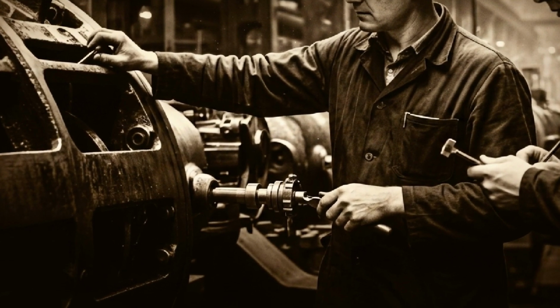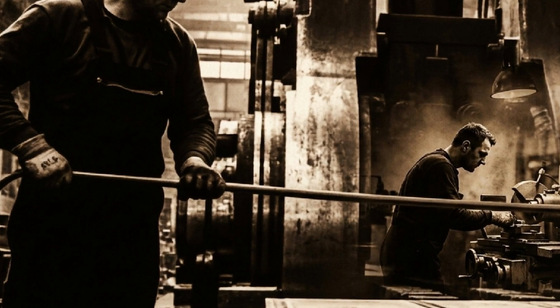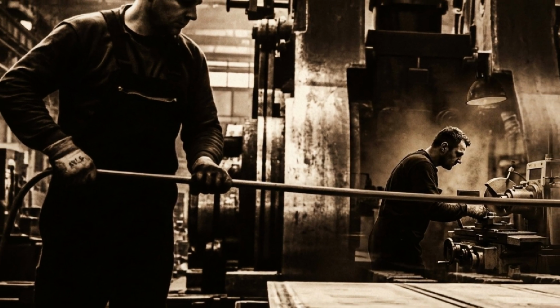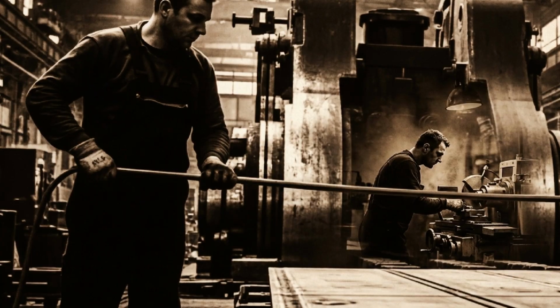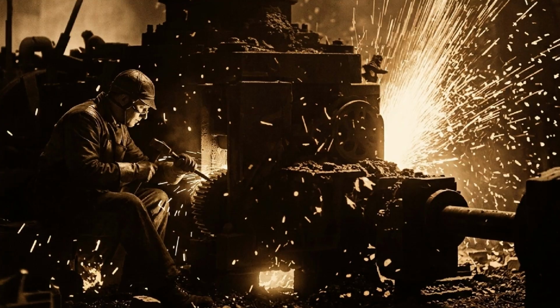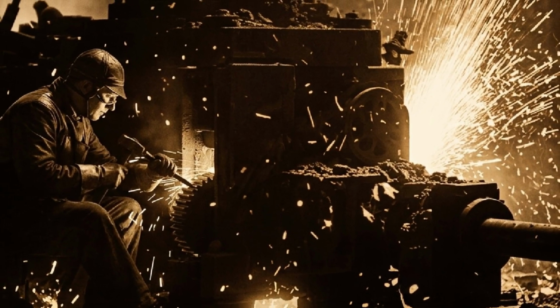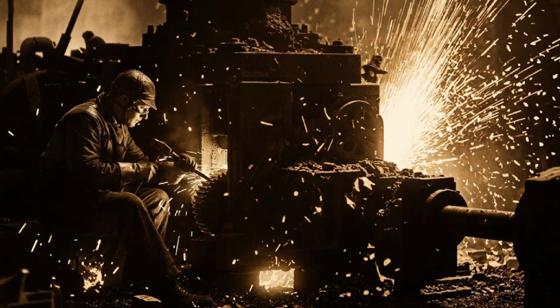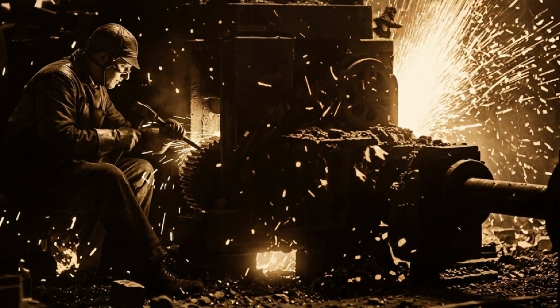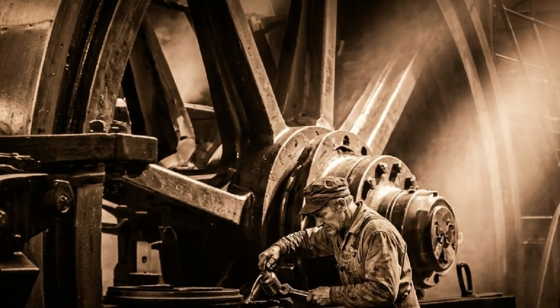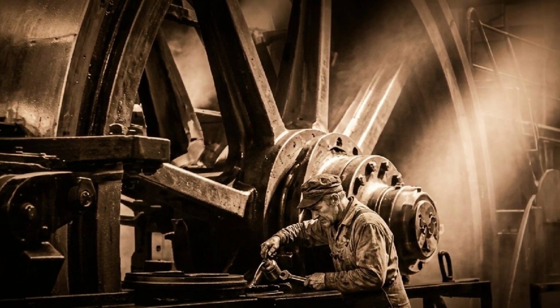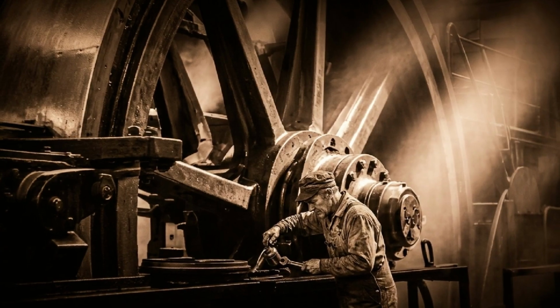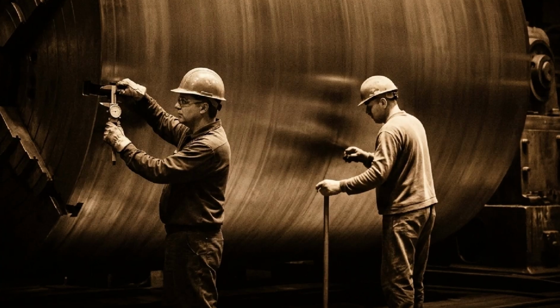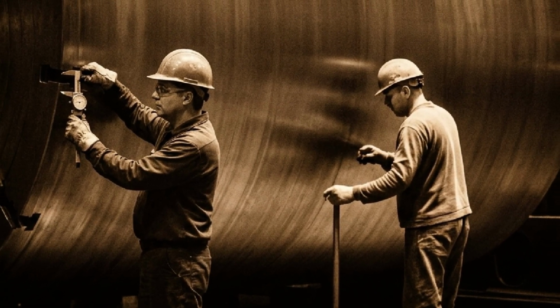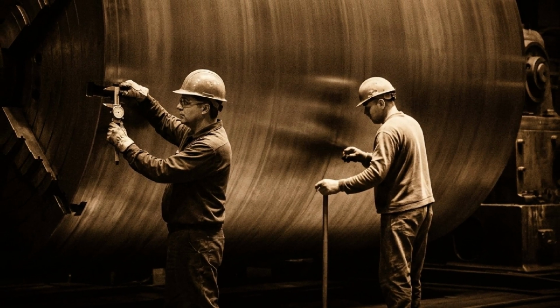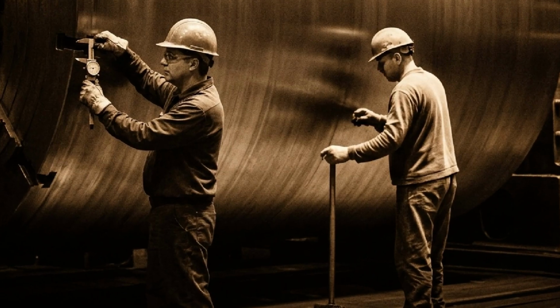To an observer, the rollers appeared unchanged. Their polished surfaces continued turning smoothly. Their dimensions remained constant. But inside the metal, microscopic structural changes slowly accumulated. Tiny imperfections formed along crystal boundaries in the steel. Under repeated stress, these imperfections could grow into microscopic cracks. At first, such cracks were far too small to cause concern. In fact, they were too small to detect, as ultrasonic testing and advanced non-destructive evaluation methods had not yet become standard industrial tools. Engineers relied mostly on visual inspection and operational performance. If the machine continued functioning normally, it was assumed to be safe. But structural fatigue does not always reveal itself externally. Inside the rotating cylinders, stresses continued building in places no one could see.